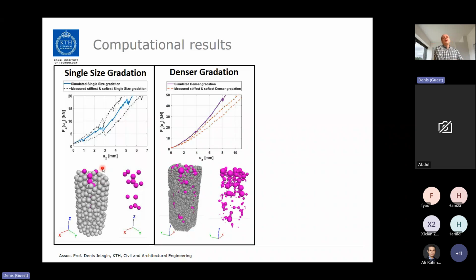Then we run our experiments and simulations for dense gradation, and this is where we have not performed any additional calibration. We use the parameters identified for the single size material. You can see that the force displacement response is captured reasonably well, except for a very high level of compaction. That's when we have quite developed breakage in the material, and then things start to deviate. We are also able to predict the distribution of broken particles within the material.